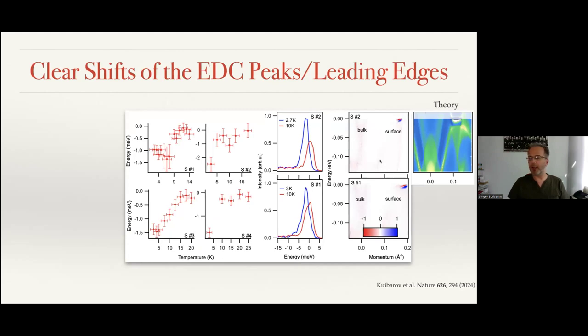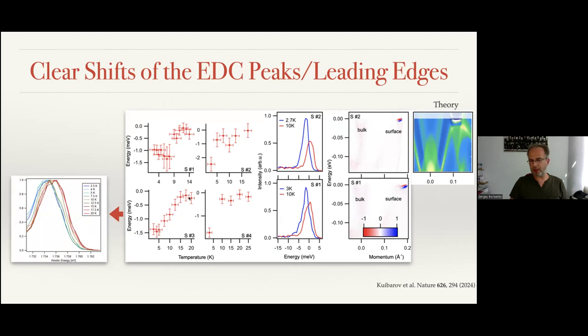at the surface. So we did it in this case for several samples. We tracked the position of this peak as a function of temperature, and typically this kind of drop indicates the critical temperature. So in this case, we showed the data for 4 samples, and the broadest transition is shown here. So this is how the superconducting gap opens.